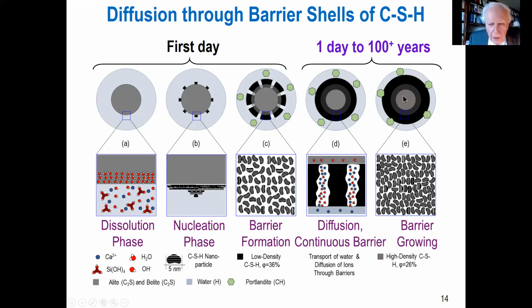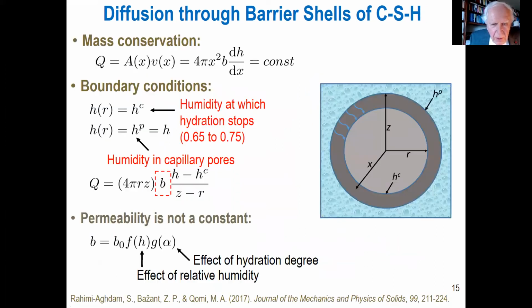The important point is that as this shell grows, you greatly slow down the permeation of water molecules. Hydration can happen only if a water molecule travels from the water, this is water vapor, through the shell to the unhindered grain surface. There it reacts, and ions then must travel outside. There must be balance, so we need water only by permeation. And this is highly impermeable, and the time of diffusion grows with the square of the thickness. So if the thickness is a few nanometers, it's practically immediate. If it grows to many micrometers, it takes a very long time, because the permeability of CSH is much smaller than concrete as a whole, where the diffusion goes preferably through the largest pores.